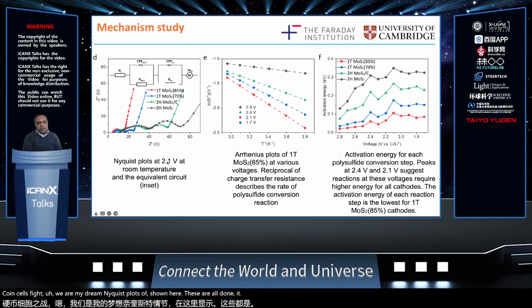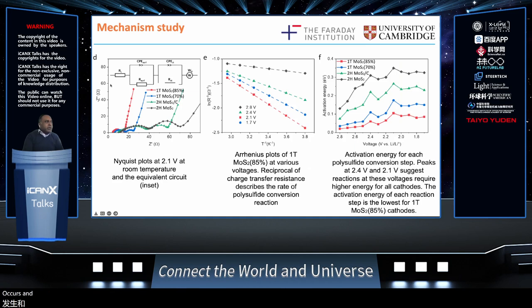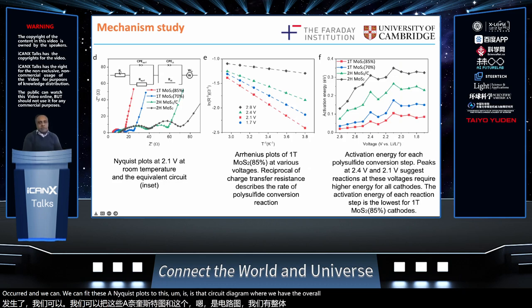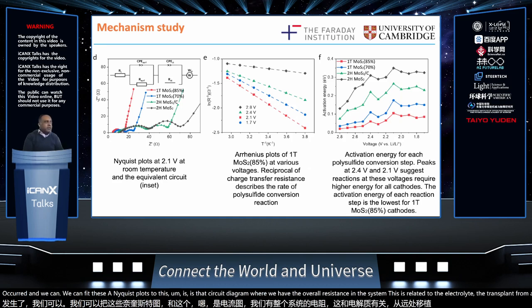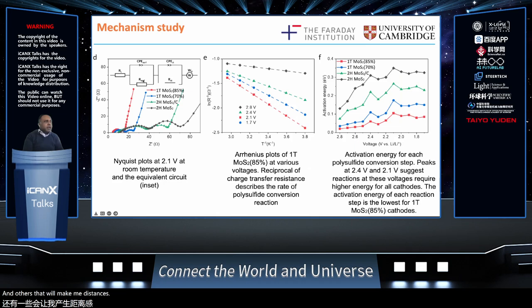These were all done at 2.1 volt because remember that is where the plateau that's responsible for 75% of the capacity occurs. And we can fit these Nyquist plots to this circuit diagram where we have the overall resistance in the system. This is related to the electrolyte, the charge transfer resistance, and other ohmic resistances. And we can also look at the resistance due to the sulfur on the electrode, et cetera. And by fitting these parameters, we obtain these curves.